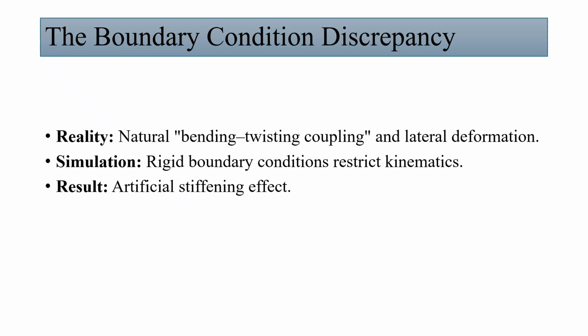In reality, off-axis carbon fibers naturally twist and slide a little bit when you bend them. But in ANSYS, our rigid boundary conditions locked the specimens in place and prevented this twisting. Because the simulation didn't let the material twist naturally, it created an artificial stiffening effect. This proves that we must be very careful with boundary conditions when simulating off-axis composites.